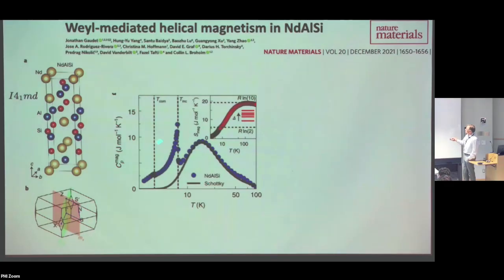And you can see this kind of broad hump. Notice it's a logarithmic scale. So this broad hump in the 20, 30 Kelvin range actually has to do with the Schottky anomaly associated with the other four doublets in this Kramers spin.